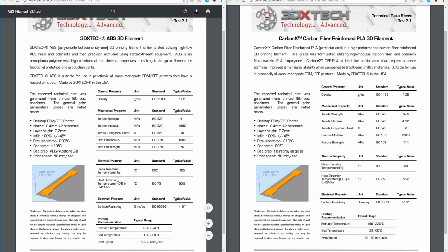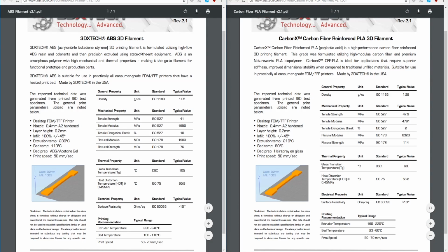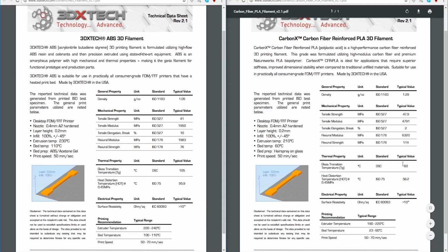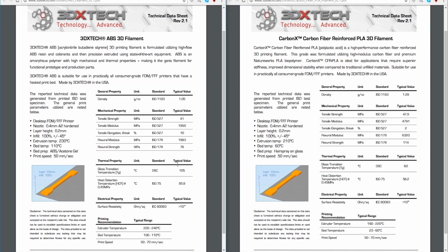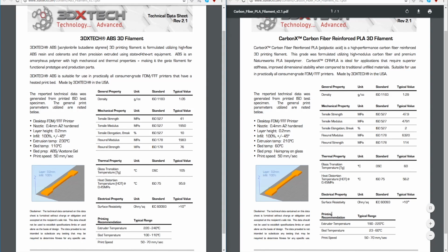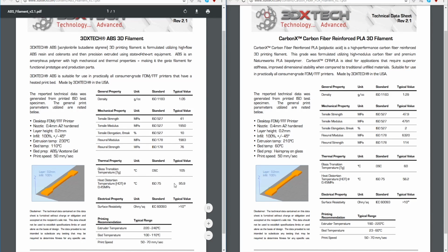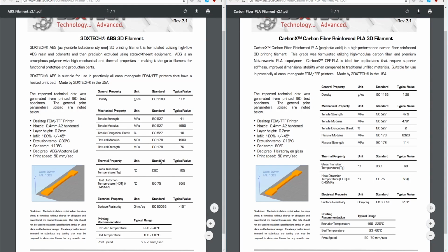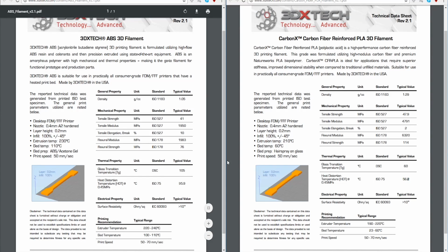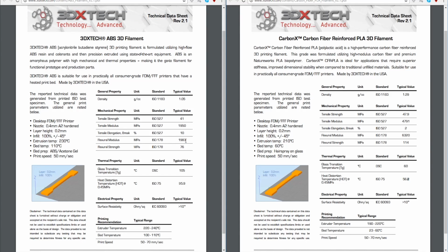But look at the dimensional stability, glass transition temperature, 105 degrees Celsius. So almost double that of PLA. So if you put this on the dash of your car, it's not nearly going to deform as much as the PLA, even with the carbon fiber filled. Here, heat distortion, again, 100. Here, 56. So again, almost double. So ABS, more ductile, definitely not as stiff, definitely not as strong, definitely not as stiff in flex, and definitely not as strong in flex.